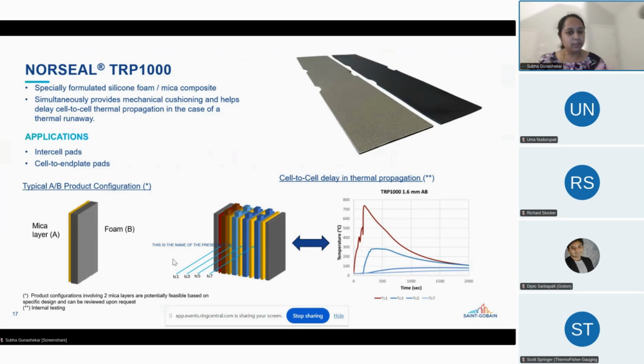This is the most basic product we offer today, which combines the mechanical and the thermal properties to some extent to delay the thermal propagation and also provide good mechanical cushioning if used in cell-to-cell applications. It's called TRP 1000. We have a mica layer and we have a foam here, a silicone foam. This silicone foam can be replaced by a polyurethane foam if the cells used are LFP cells, where your temperature range wouldn't exceed more than 600 degrees. Whereas if it's NMC, your temperature ranges are more than 600, close to 800 or 1000. So we would go with silicone in those cases. So this is one of the key products we've introduced to manage cell-to-cell thermal and mechanical propagation.